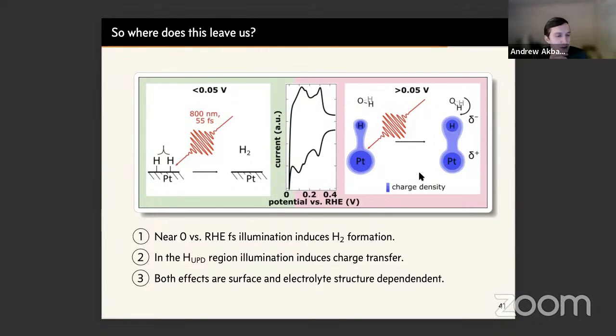I guess the question is whether your laser pulse can change the double layer structure such that you drive it out of equilibrium. I presume that it shouldn't, because the time scale is very different. The thermal excitation that it brings into the double layer, which restructures as a result, is on a longer time scale than your actual charge transition.